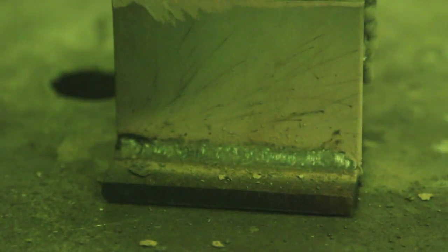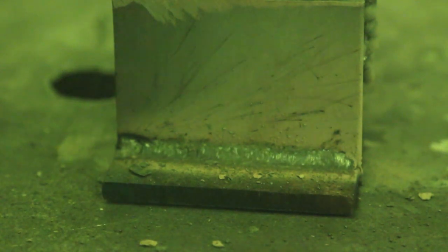Anyhow, there we go. We are cleaning off the weld. The slag has come off very easily, which is always a good sign. And upon cleaning this guy up a little further, you notice we have a nice, bright, shiny weld with a decent ripple pattern. And it appears, once we see it here, that everything looks pretty good. Good fusion all the way across, and a pretty even weld.